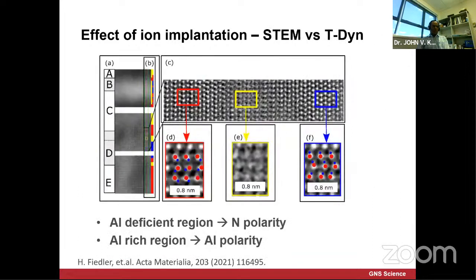If we go down, then we look at the high-angle annular dark field scanning transmission electron microscopy, called HAADF-STEM image, which is sensitive to atomic mass. Initially at the bottom of the material, the aluminum polarity is red, and then the nitrogen polarity is inverse, kind of blue. So this is actually quite good. You can see those different regions, how the defect-rich regions based on the zirconium implantation show multiple polarity changes from one region to other regions when defects occur.